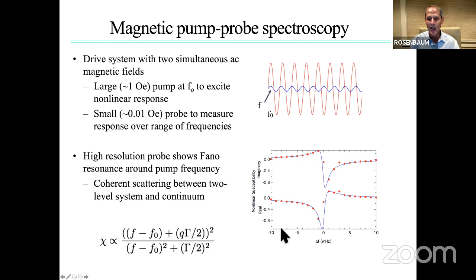This is the imaginary part on the top, the real part on the bottom. What you see is basically the hole in the spectrum. The hole in the spectrum can be fit by a Fano form, which means there's coherent scattering between the 2-level system and the continuum. And this is the Fano form. I don't want to go through that. This, of course, was developed for atoms by Ugo Fano, talking about the quantum interference between excitations inside the ion and then full ionization of the atom. And there are 2 parameters here which I want to point out to you. One is the line width, that's gamma. The other is the Fano asymmetry parameter, small q.